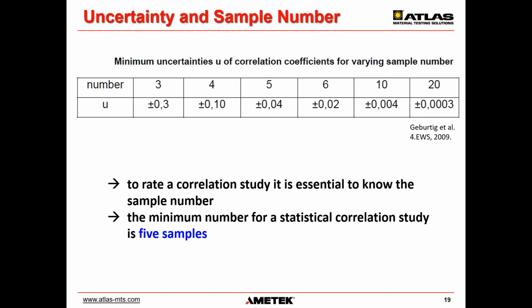So 3 is definitely not enough to do a correlation study. The uncertainty is just too high. If you have more specimen, the uncertainty decreases. So if you have at least 5 specimen, the uncertainty is plus minus 0.04, and that's, I would say, an acceptable uncertainty. It's not perfect, but it's an acceptable uncertainty.